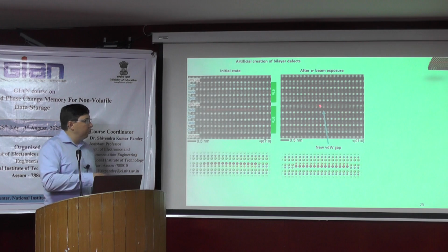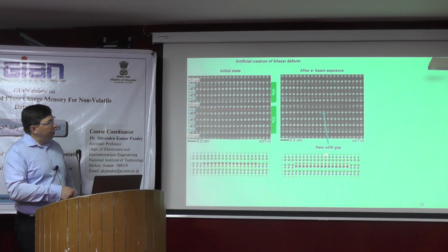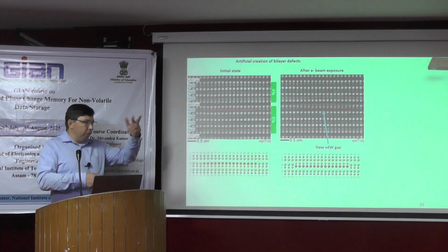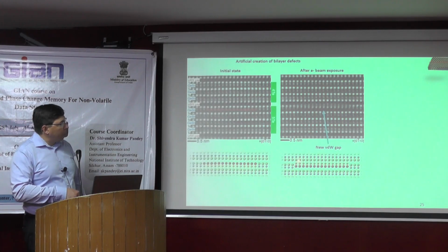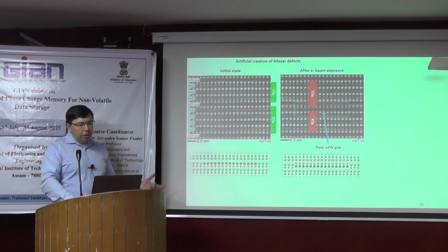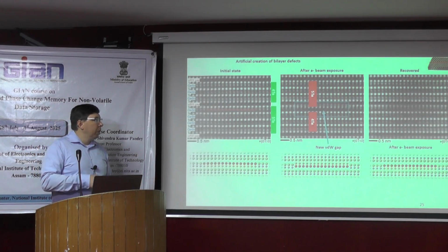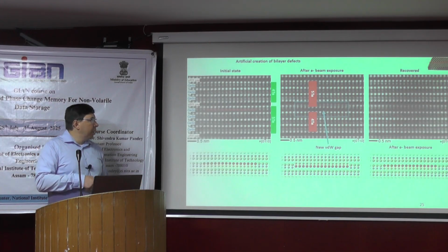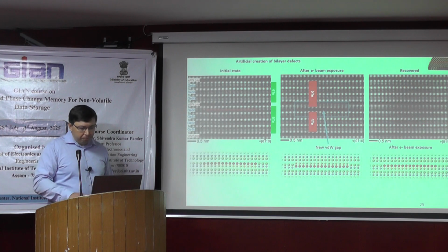directly in the microscope. Here you see this is the initial system, and then this is rotated, so the two layers are flipped, rotated, and then you see here also such a formation, such a bilayer defect. And then the system is also reconfigurable. You can also bring the system back to the initial state if you expose this area again to the electron beam.